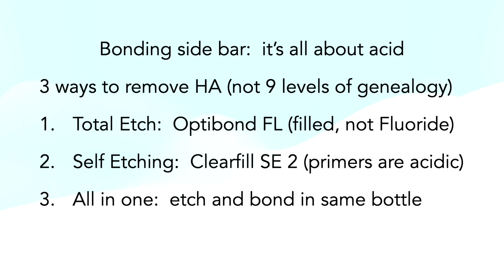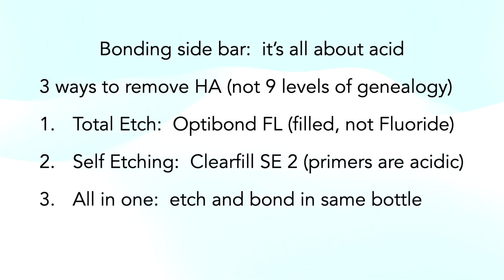Okay, sidebar, and this gets almost to your question. How do you remove hydroxyapatite crystals? Well, you do it by applying an acidic solution. There are 3 ways of doing that. One's total etch with phosphoric acid. Second way is with self-etching systems. Bottle 1 is the acidic medium that is dissolving hydroxyapatite crystal, except we don't wash it off. And within that family of self-etching primers, you can have lightly acidic, medium acidic, and highly acidic monomers. And then the third way of dissolving the hydroxyapatite crystals is using the all-in-one bottle, where it has the acid and the bonding agent together.